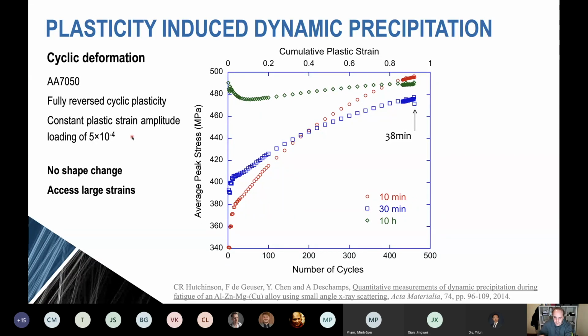And so in this case, we're making the dislocations go back and forth in the material, but we're controlling the amplitude of that back and forth motion of the dislocations. And what I'm showing here is the average peak stress as a function of the number of cycles of deformation. And I've got three different states. The green one, this is the peak age state. It already has a very well-developed precipitate state. Almost all the solute has been taken out of solid solution and made into precipitates. And that is pretty stable cycling. The stress is pretty stable as a function of the number of cycles.